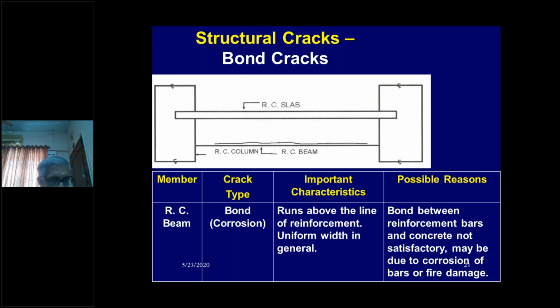Bond cracks, nothing to do with James Bond. These are bond cracks where corrosion has occurred in the bars, and once corrosion occurs, it debonds from concrete due to the formation of rust. And this is a very, very well-known phenomenon in any coastal area of India, that the bars start rusting and start debonding, and the resultant cracks allow more water to go in, and create problems. It can also be due to fire damage.